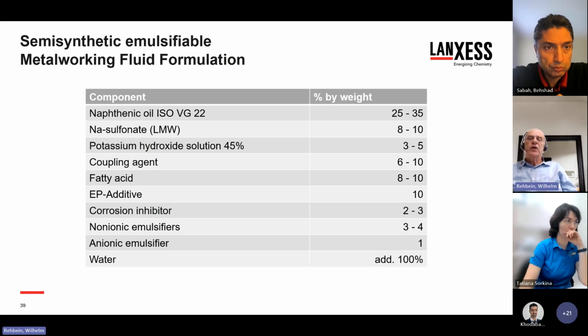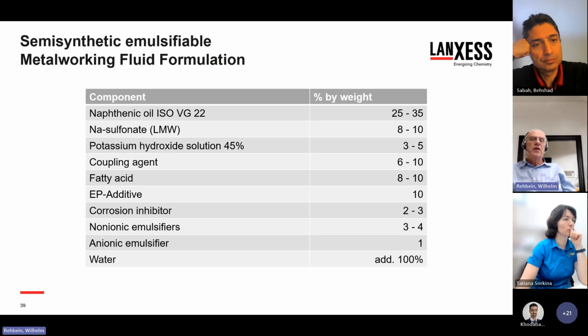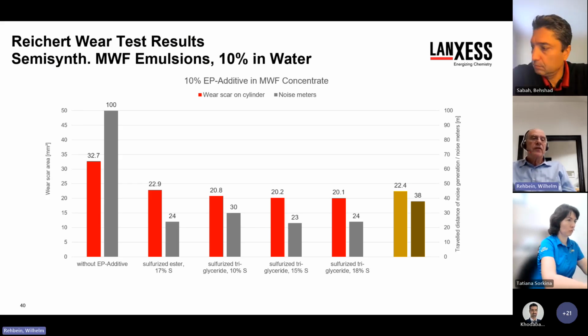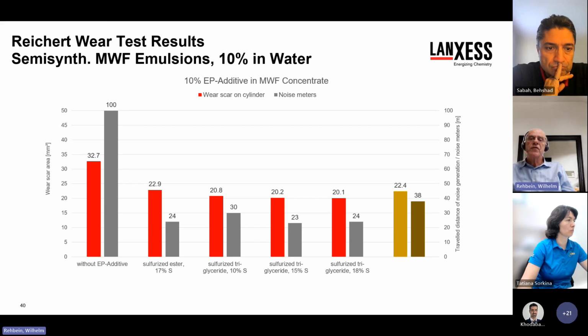This is just the guideline formulation of the emulsifiable semi-synthetic metalworking fluid concentrates that we used, containing naphthenic oil. And all the EP additives were added with a treat rate of 10% to these emulsion concentrates. So these are the test results, and compared to an emulsion without EP additives, there's a clear reduction of the wear scar diameters, the red bars, and also the noise meters when adding 10% of a sulfur-based EP additive to the emulsion concentrates.